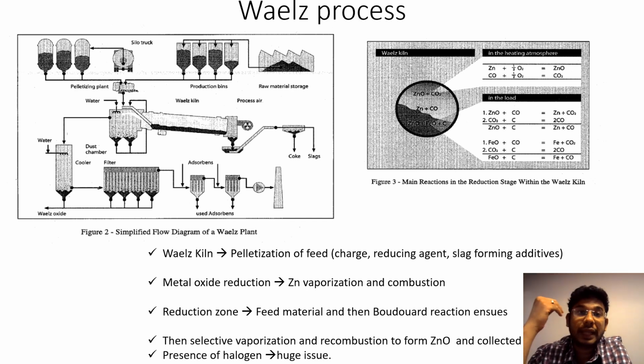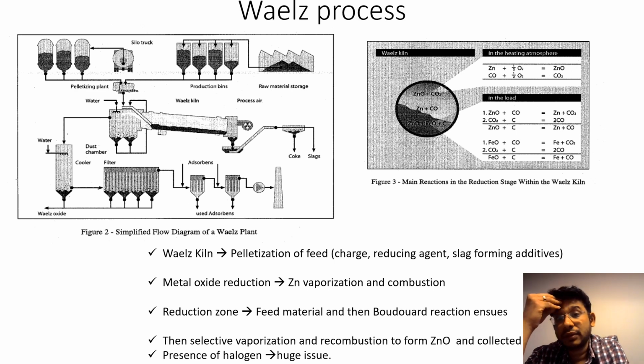So that is why, and because the Waelz process also has this limitation where you have to have at least 18% of zinc in the input feed. I think that's the number, 18%. Here's the key issue: EAF dust is also very diverse. Sometimes you have less zinc, then you have to play around with your dust so that it fits in the Waelz kiln.